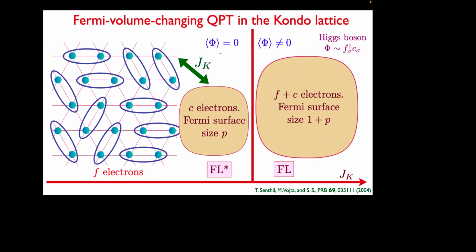Just to give you a very simple picture of how you could get a change in the volume of the Fermi surface without any broken symmetry, you can imagine a two-band system called a Kondo lattice. You don't have that in the cuprates, but allow me that simplification. One band forms a spin liquid, like an Anderson spin liquid, and the other band forms a Fermi surface. Now you turn up the coupling between them. You need a finite coupling before the so-called Kondo effect takes over. The electrons tend to screen the spins in the so-called Kondo screening cloud, and that leads to what's called a large Fermi surface, where it counts all the electrons. This is where the Luttinger rule applies, whereas here you violate the Luttinger rule, but you have a spin liquid around.